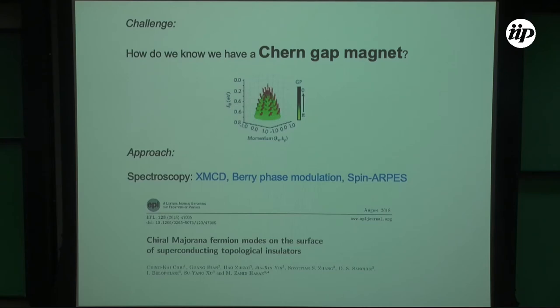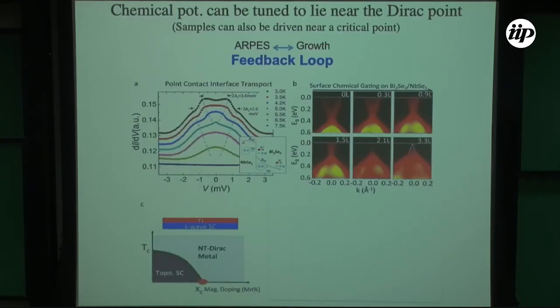Yes, that's a very good question. We tried that early on. We took a high-Tc compound, say a cuprate d-wave, and put a bismuth selenide topological insulator on top, and tried to see whether d-wave pairing is induced on this Dirac surface state. And that experiment, as I was telling colleagues at lunch, is one of the many failed experiments that you don't hear about because there's no result. It turns out that all these cuprates have Fermi surfaces like this, whereas the bismuth selenide Fermi surface is here at the gamma point, where you have a Dirac thing.